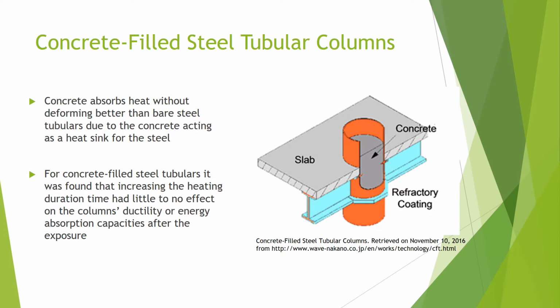Concrete-filled steel tubular columns. Concrete absorbs heat without deforming better than bare steel tubulars due to the concrete acting as a heat sink for the steel. For concrete-filled steel tubulars, it was found that increasing the heating duration time had little to no effect on the column's ductility or energy absorption capacities after the exposure.